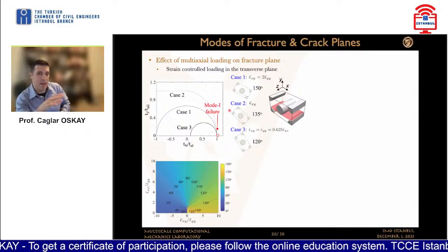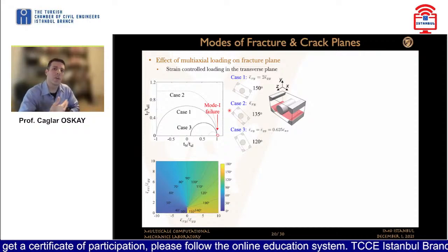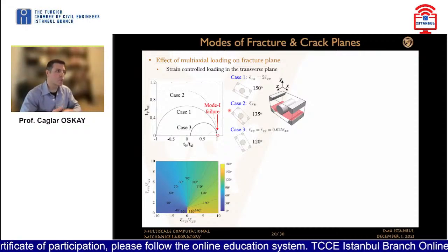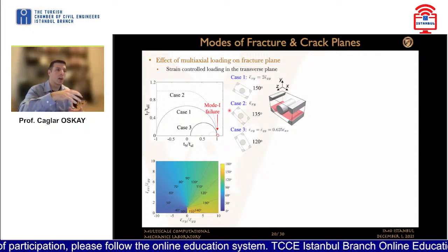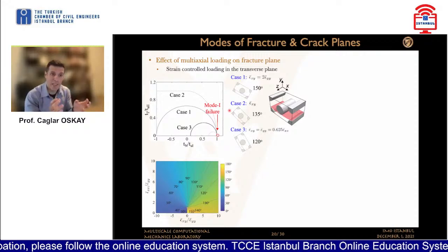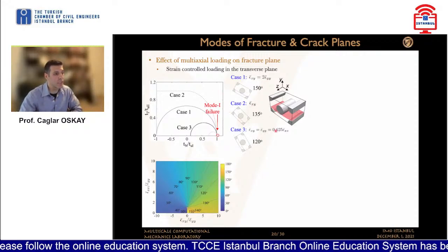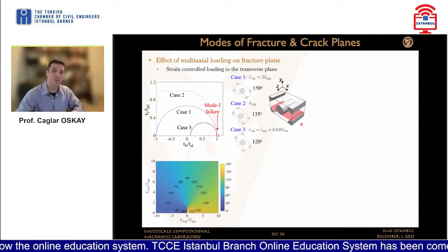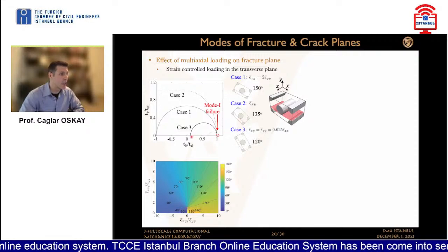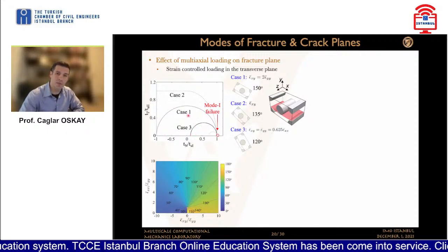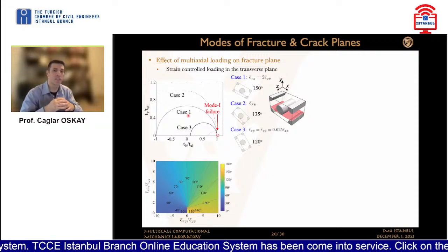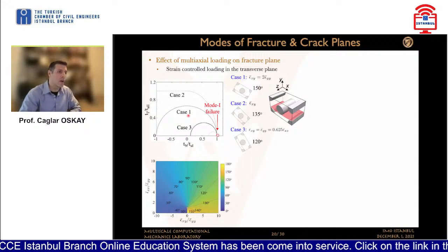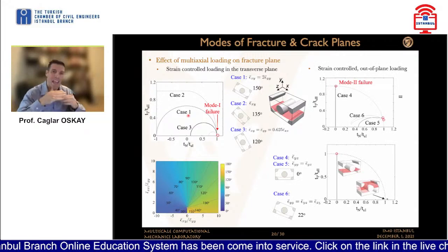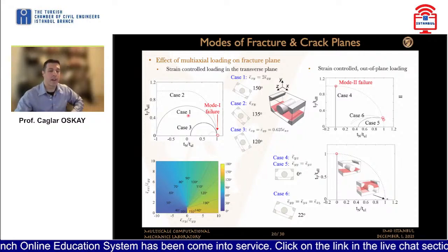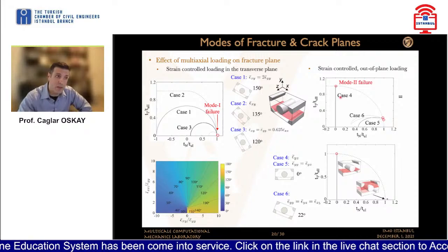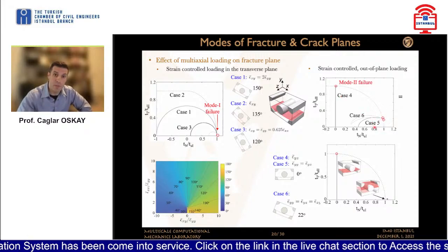So we have conducted some interesting studies to understand the mode of failure based on this approach, where we are looking at microstructures and loading them in different load orientations in multi-axial conditions. For example, we're showing 3 different types of loads. These are in plane, which induces matrix cracks. And as you can see, most of the failures that we've observed in in-plane loading conditions have been mode 1 separation failures. Now, if you start incorporating out-of-plane loads, then we found it was possible to create mode 2 failure as well as mixed mode failure.